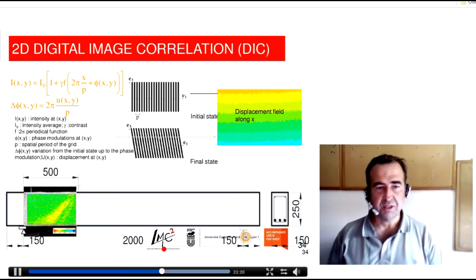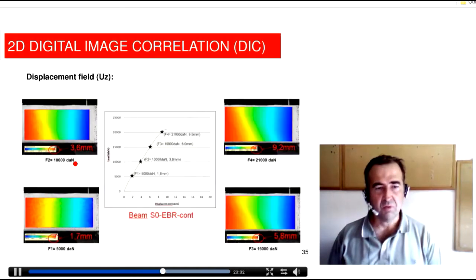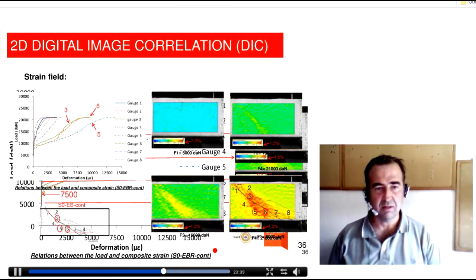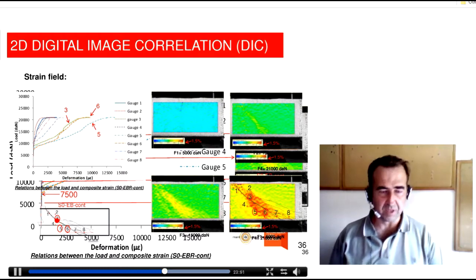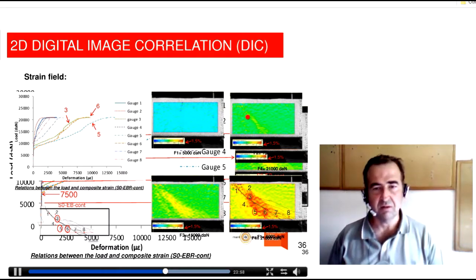So in order to better understand how the strain is distributed in the flax fibers, we use a DIC method in the cracking area. In this way, we are able to get strain and stress curves for different levels of load and obtain in that way the different cracking pattern. So what you observe here is we compare this also with strain gauges locally bonded onto the FRP system. And what you observe is that cracking propagates very nicely under the flax fibers, and then at the end we obtain the failure of the strip in this area where the tensile properties are the higher.